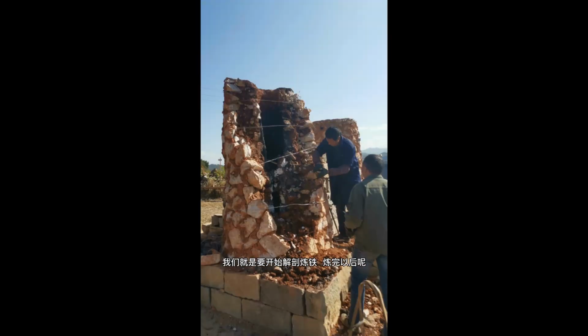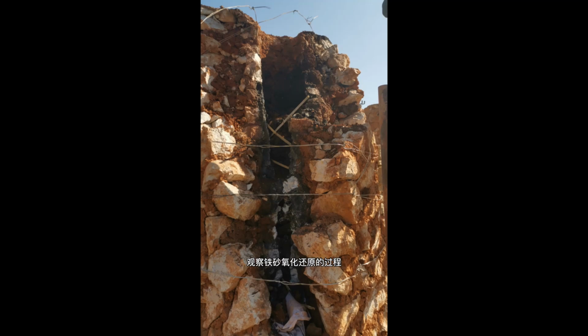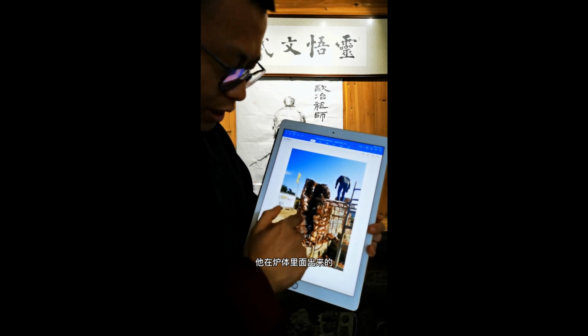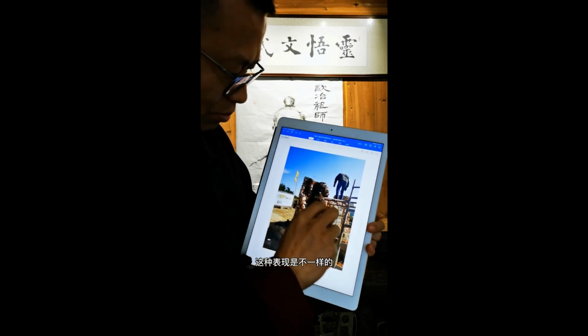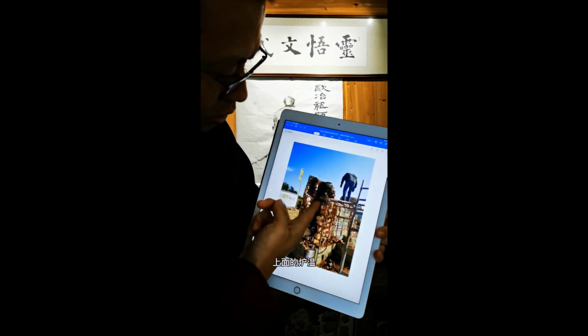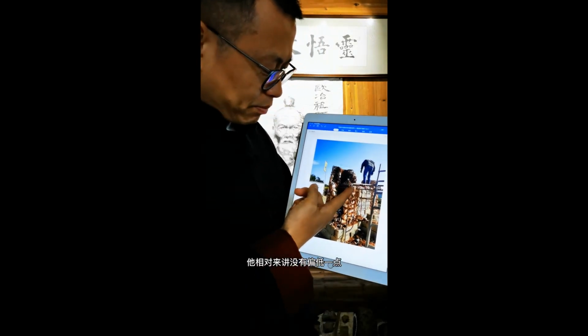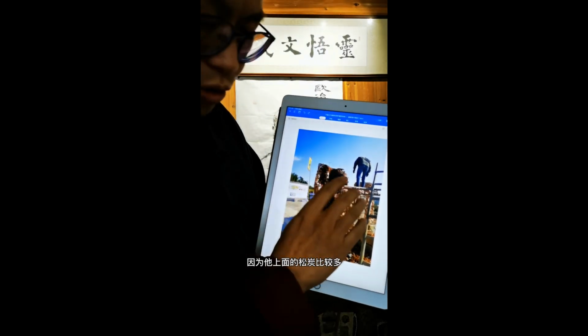In step 6, we also conducted dissection of the furnace to study how temperature changed in the furnace. We observed how iron sand got oxidized and reduced. See, this is a dissection of the furnace. The upper side and the lower side, the temperatures were different in the furnace. So therefore, you can see different signs of burning in the furnace.